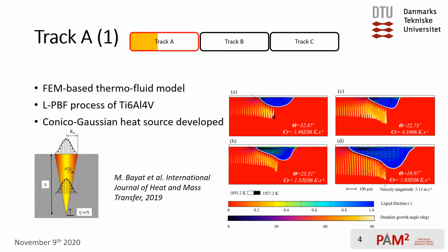For example, in one of the studies belonging to the first investigation track, I developed a FEM-based thermo-fluid model of the LPBF process of titanium-6 aluminum-4 vanadium, where I developed a conical Gaussian volumetric heat source for modeling the laser-material interaction. And then finally, I studied the impact of beam size and also the scanning speed on the melt pool morphology, cooling rate, and the dendritic growth directions.